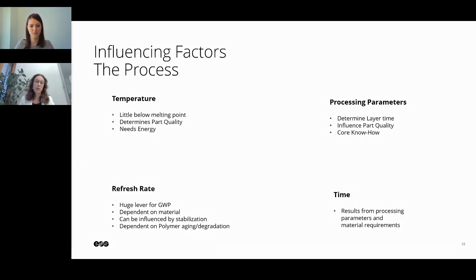And lastly, I've got the time. The longer my process runs, the more energy I need, especially for heating. So this is a result from the processing parameters and the material requirements. Summarizing this, the temperature, the processing parameters, and the refresh rate all have an influence on the part properties, meaning mechanical properties as well as surface properties. So how much detail I have and how clean and even my surface is.